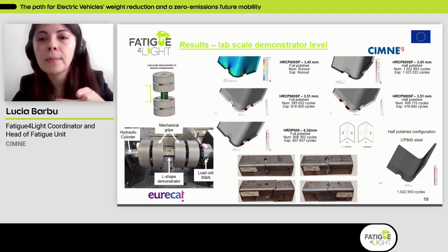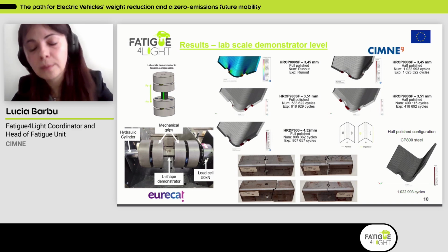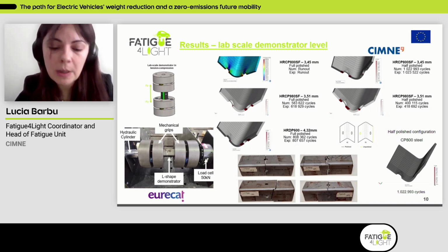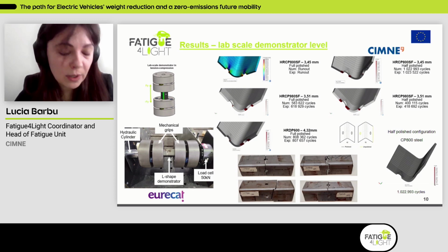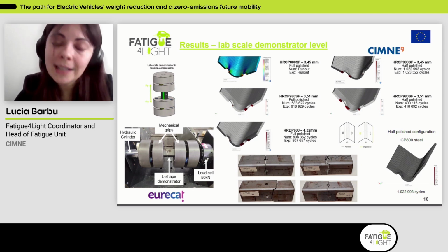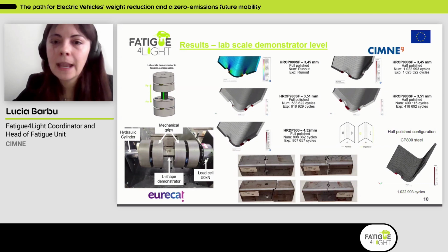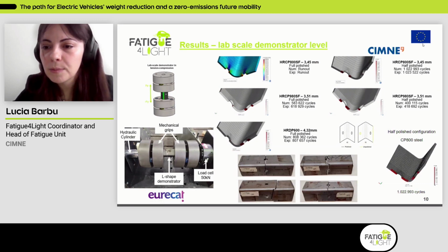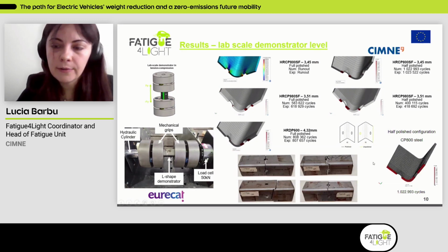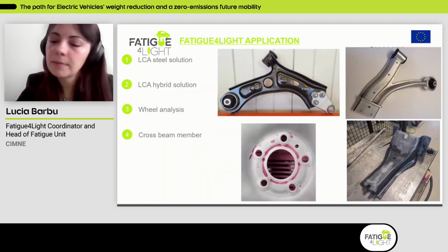and also an image from the numerical campaign that CIMNE performed on these specimens, because our ambition was, with the fatigue numerical formulation that we have developed, to capture correctly the fatigue life, the number of cycles until failure, but also to capture correctly the crack propagation. So not only the initiation under the cyclic loading, but also how this crack progressed. And you can see here also just a small simulation of crack propagation. Again, more details about numerical simulation later on in the technical session.